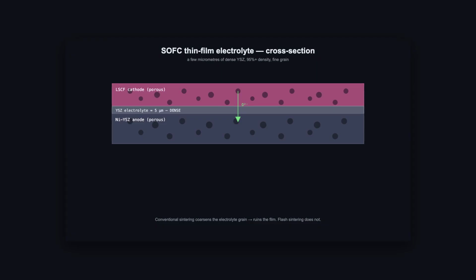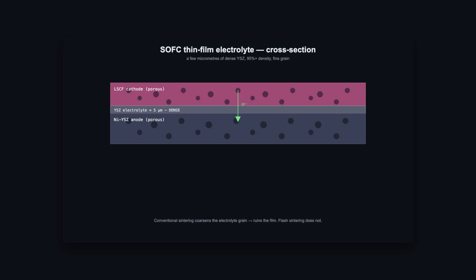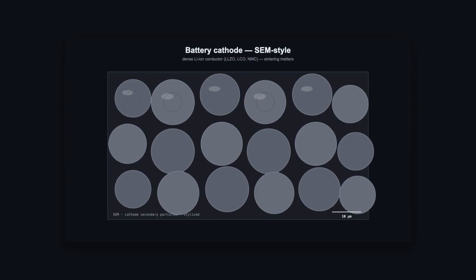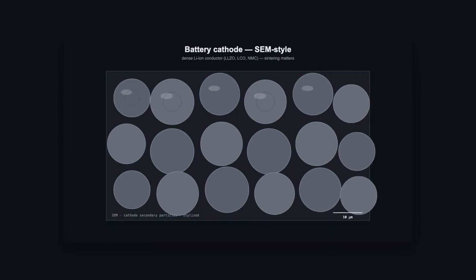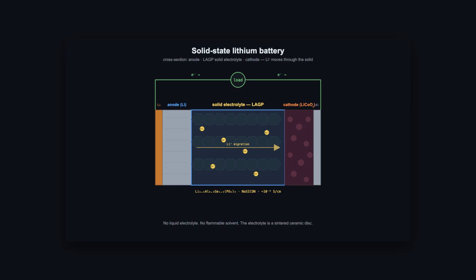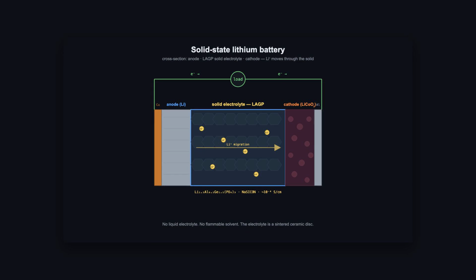Solid oxide fuel cells need dense, thin electrolytes, a few microns of zirconia. Conventional sintering coarsens the grain and ruins the film. Flash sintering, in seconds, can densify it without coarsening. Next-generation battery cathodes need dense lithium-ion conductors. Same story. And on the electrolyte side, the LAGP that Campos and Rodrigues flashed in 2022 is a candidate solid electrolyte for all solid-state lithium batteries. Their flash-crystallized samples hit room temperature ionic conductivity of 2.26 times 10 to the minus 4 Siemens per centimeter. Higher than the same composition prepared by 12 hours in a conventional furnace. Faster manufacturing, better material.